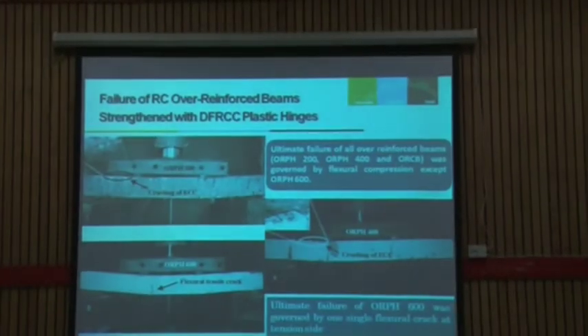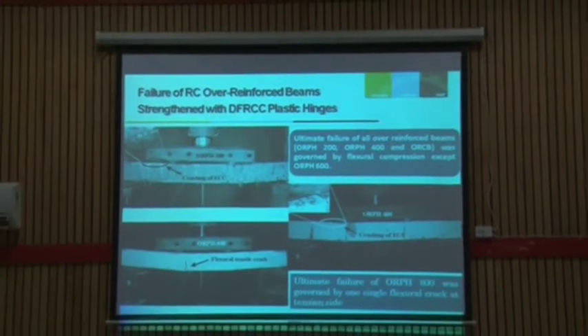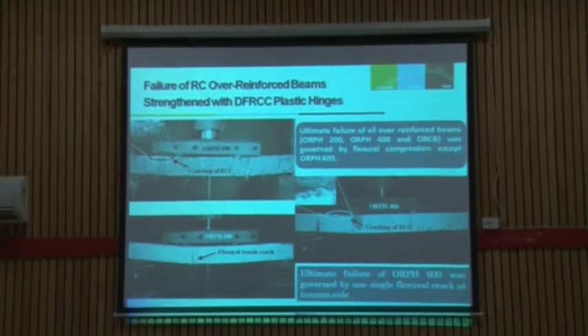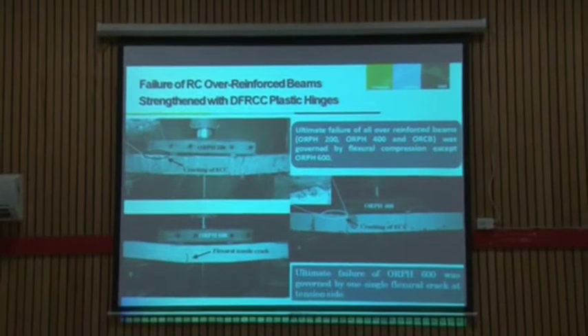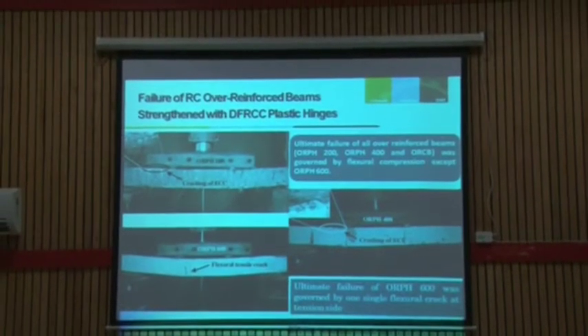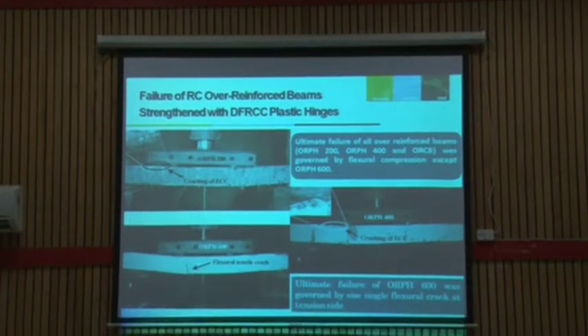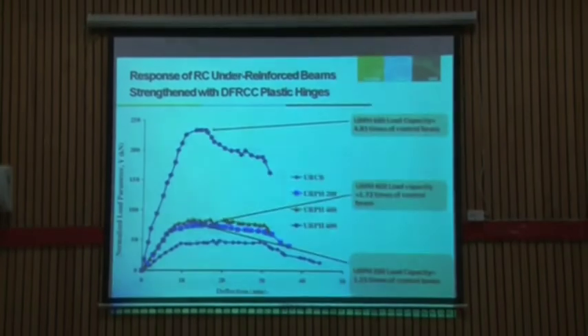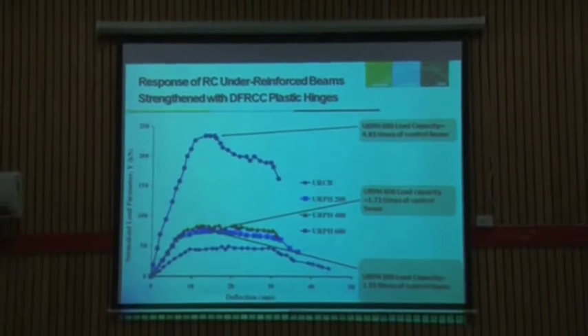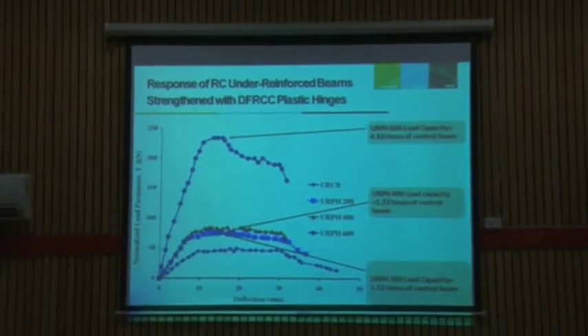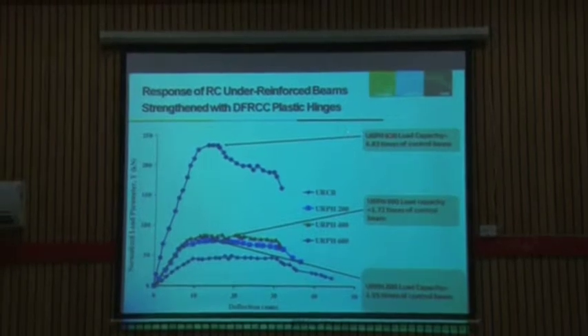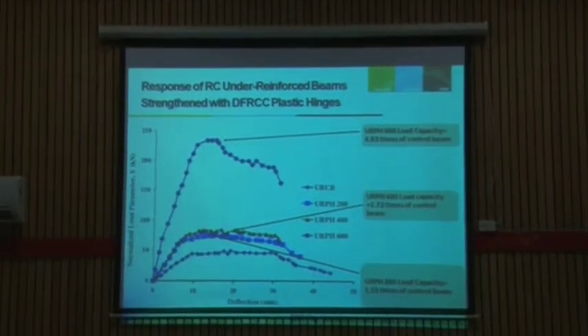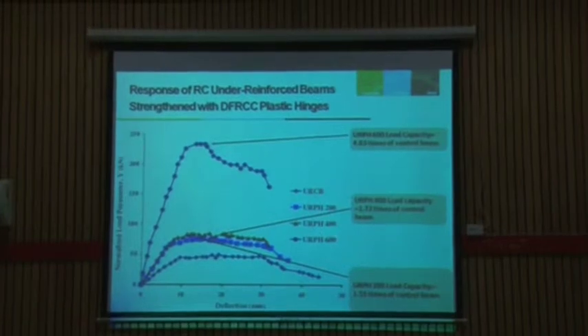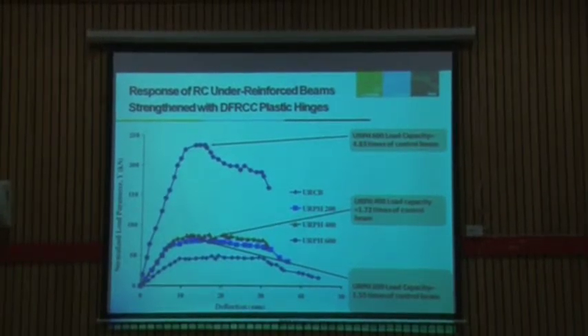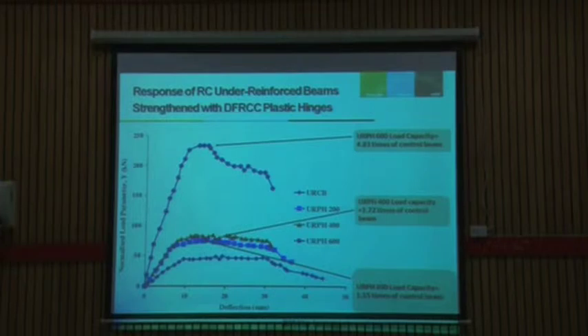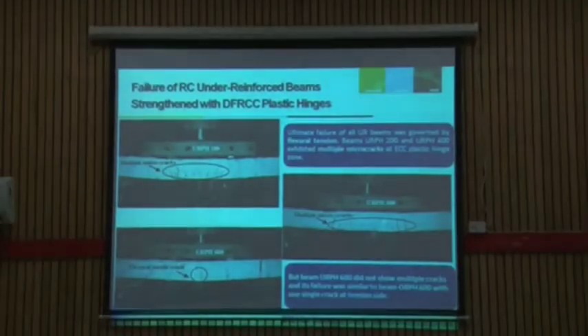Similar observations have been made for ductility failure, although we got very good strength with the 600 mm plastic hinge length, a localized crack developed at the time of failure. In other cases, multiple cracking has appeared. Similarly, for under-reinforced beams, much better response is achieved in the case of the plastic hinge of length 600 mm. For other plastic hinges, we are not getting significant improvement, but for the 600 mm length of plastic hinge put at mid span, we are getting very significant strength. There are some modes of failure.